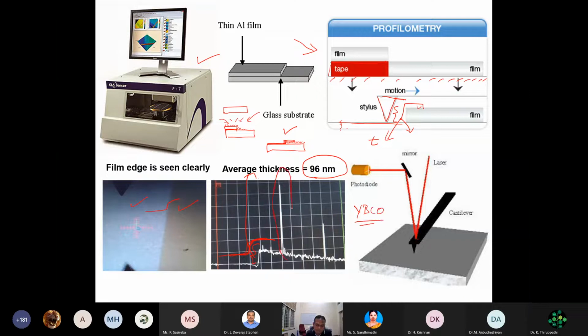You can see some spikes here. These spikes are sometimes noise. Suppose your surface is not clean, say you stored the sample for quite a long time, some small particles or paper particles from your tissue paper may be sitting there. So you have to clean the surface first before making the measurement. You can use an inert gas atmosphere to clean the surface, so that you can avoid this kind of artifact. So this is basically the step edge, and that will give you the film thickness.